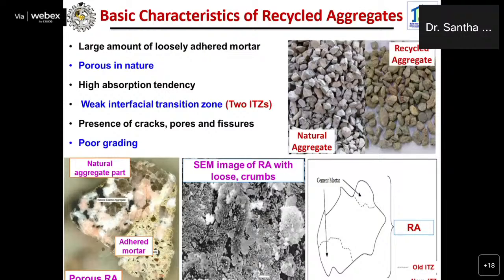Now, IS 383 already suggests utilizing recycled aggregates 100% in concrete for making lean concrete. But it is suggested to use only 20 to 25% for making plain cement concrete, as well as reinforced cement concrete. So our motto is to use 100% of the recycled concrete aggregates for making structural concrete. In these aspects, at CBRI, we have been working in the last decade.